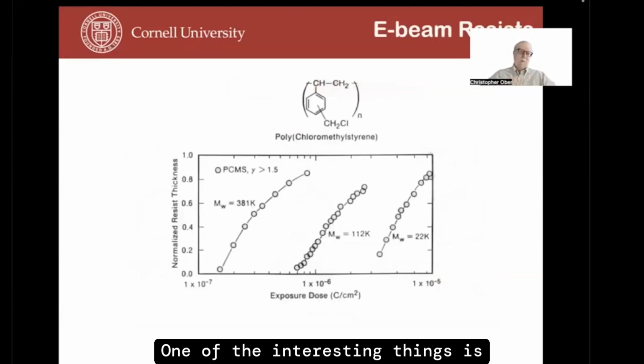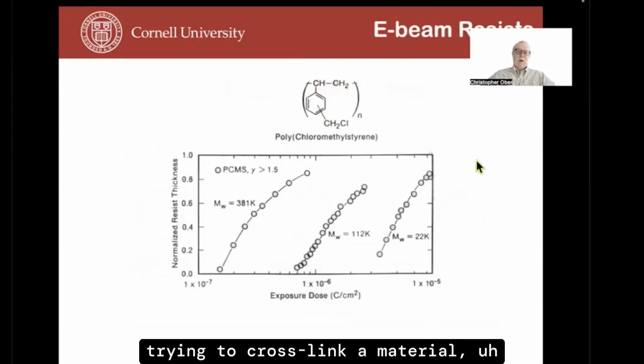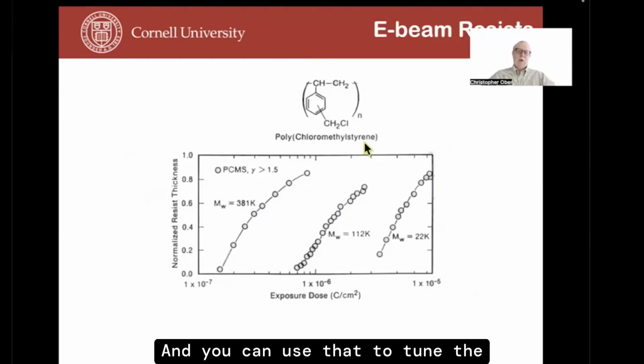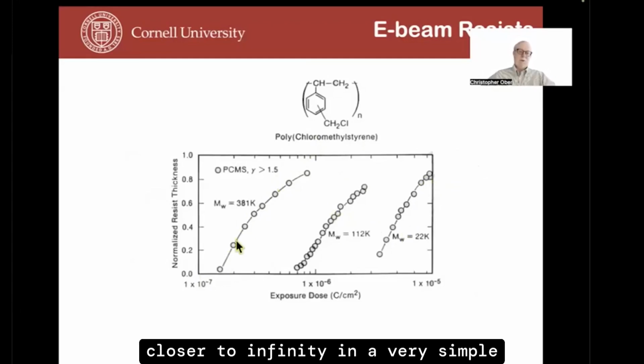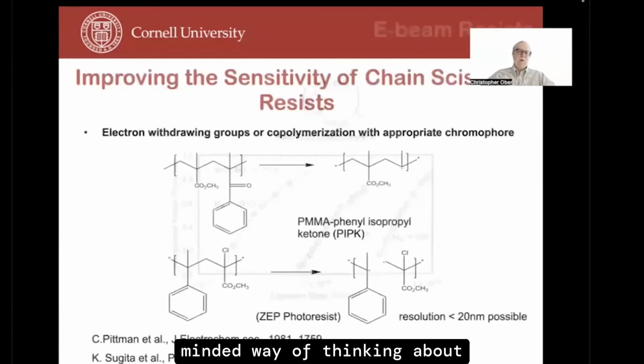One of the interesting things is the sensitivity of these different polymers. And it turns out if you're trying to cross-link a material, you want to have a higher molecular weight. So molecular weight is something that you can build into a higher or lower molecular weight you can build into a photoresist system, and you can use that to tune the performance. This particular table, the way I look at it is that if you want to make something insoluble, you want to build up the molecular weight as close as you can to infinity. And so something that has a 300,000 molecular weight versus a 22,000 molecular weight, if it has a higher molecular weight, it's closer to infinity in a very simple-minded way of thinking about resists.